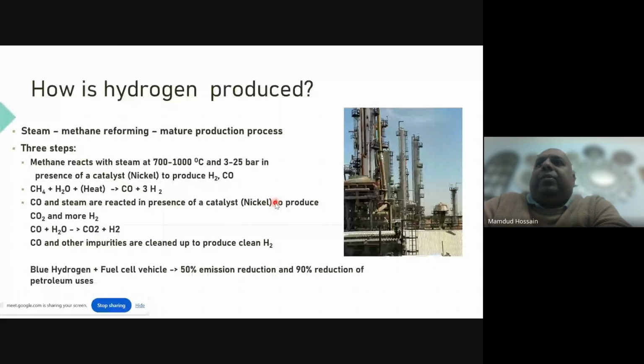Anyway, let's look at how we can produce hydrogen in an industrial space. This is actually a very mature technology. It has methane. We mix it with steam at 700 to 1000 degrees Celsius under a pressure of 3 to 25 bar, and in the presence of a catalyst. We need a catalyst called nickel to produce hydrogen and carbon monoxide in the first step. So you get your methane, you get your steam, apply heat and pressure. In the presence of catalyst, it produces carbon monoxide and hydrogen.